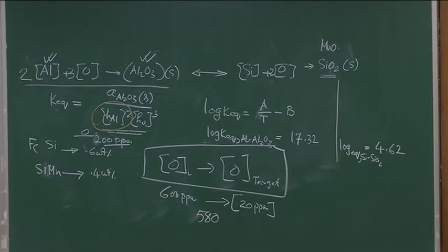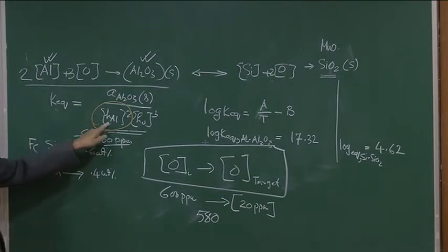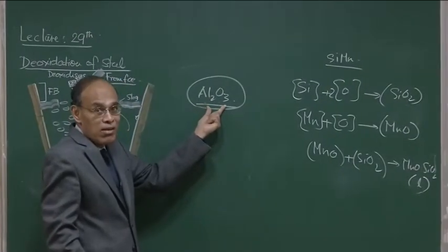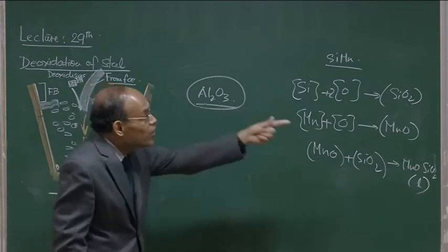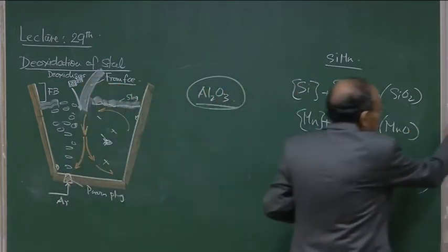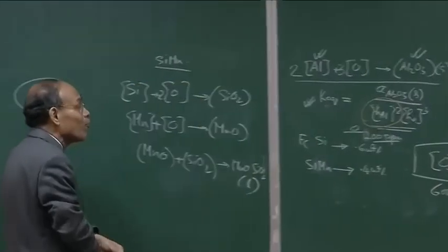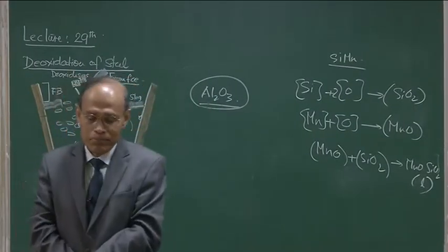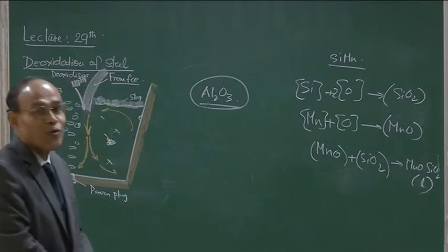So, therefore, we should be able to calculate aluminum, and then once we calculate the Henryan aluminum, we can convert it into weight percentage, and then we add these two components up: the aluminum tied up in alumina as well as the dissolved aluminum calculated from thermodynamic equilibrium at the given temperature. Sum the two up, and that is your total aluminum requirement for the process.